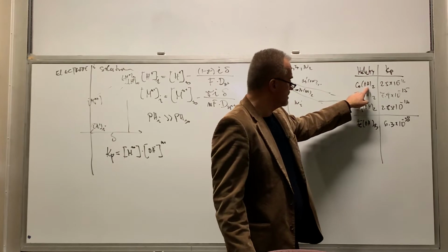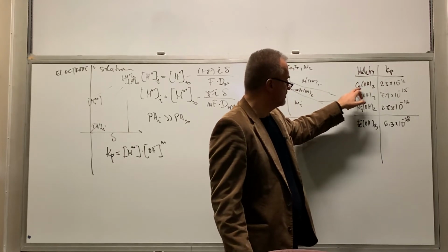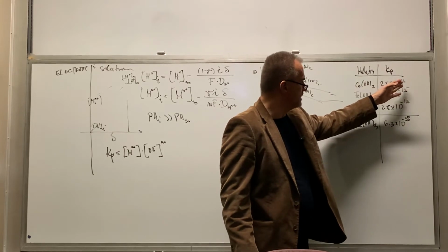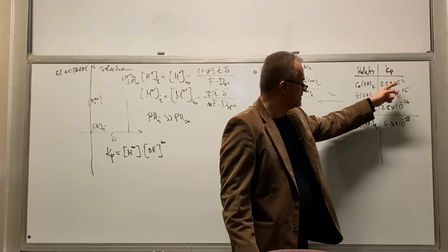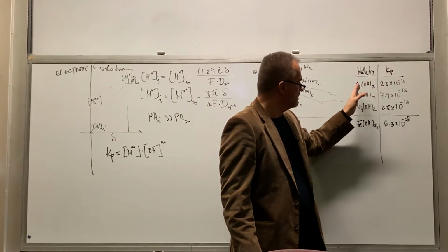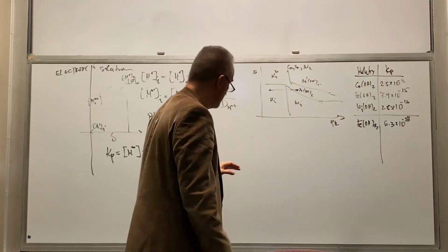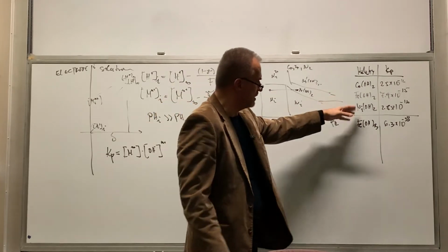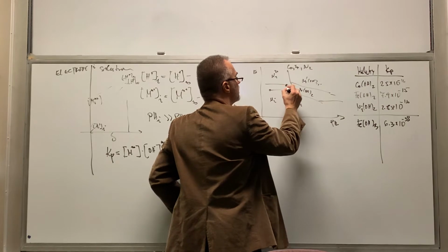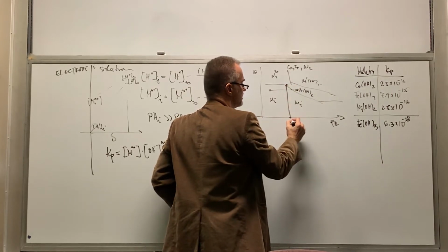So that means that if I have cobalt, let's say 0.1 molar, that is 10 to the minus, let's say 15. The square root of 10 to the minus 15 is of the order of 10 to the minus roughly 7. So that means that cobalt hydroxide, roughly, according to the Pourbaix diagram, and the same for iron hydroxide and nickel hydroxide, will not show up unless you exceed pH around 7.